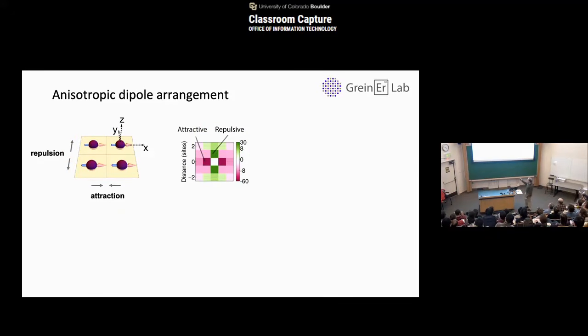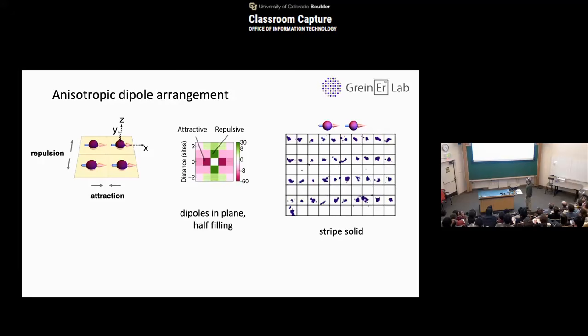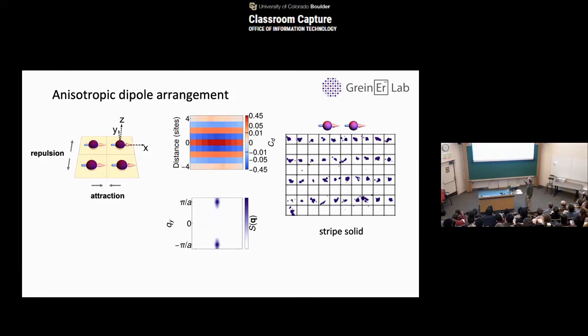And in a similar fashion, if the dipoles are now in the plane, so they attract and repel, what's the ground state now? Well, of course, you would expect some stripes, right? Like this. And in fact, yeah, that's a picture. That's the kind of pictures we can take. And here the fidelity is a bit higher, actually, because this attractive interaction is twice as big as the repulsive interaction. And so we can get this striped ordered state.